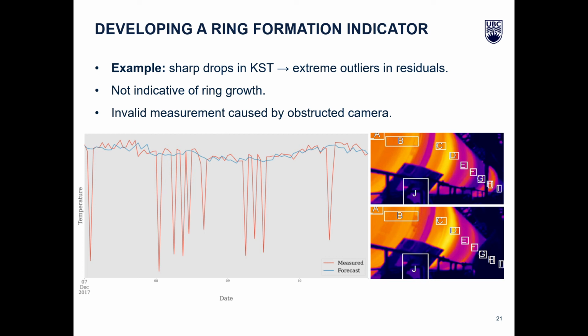By validating our residual with the raw images, we can see that these residuals are not indicative of ring growth. Instead, this is an example of an invalid temperature measurement caused by an obstructed camera. This example demonstrates some of the confounding factors that create difficulties with inferring ring growth from shell temperature changes.